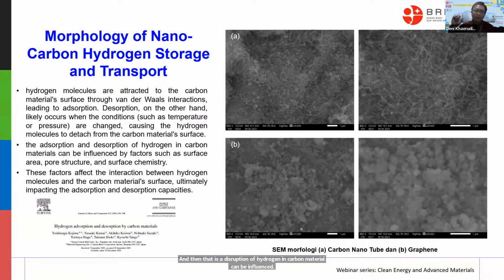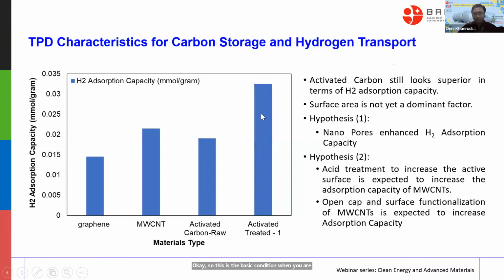Can be influenced by factors such as surface area, pore structure, and surface chemistry itself. Meaning, we can also load it with some catalysts like nickel, Pt, or many others, but only in a small percentage. And this factor affects the interaction between the hydrogen molecule and the carbon material surface, ultimately impacting the adsorption desorption capacity. Okay, so this is the basic condition when you are interested in doing hydrogen storage based on carbon material.